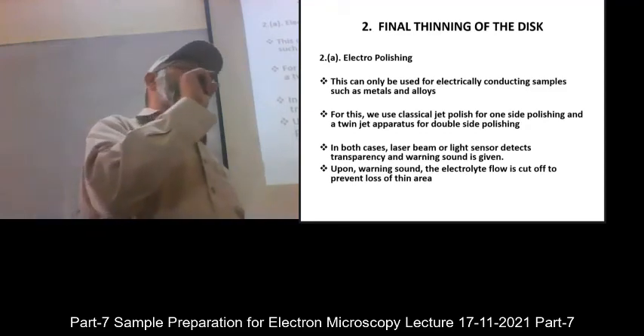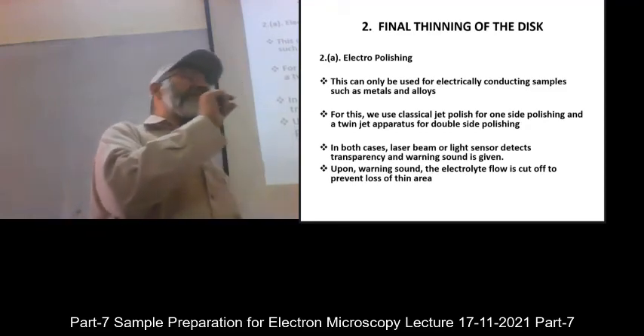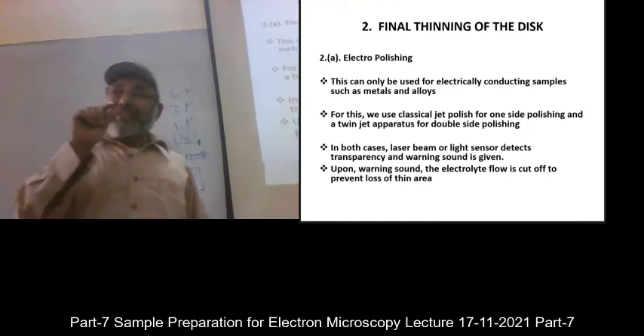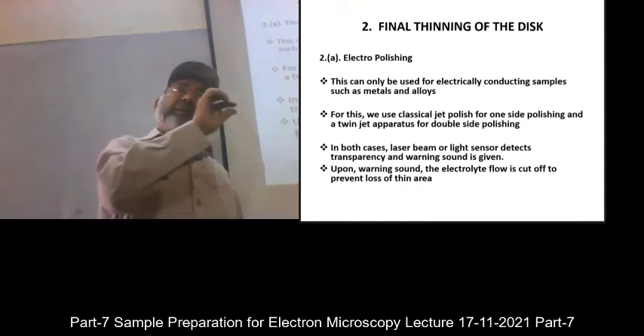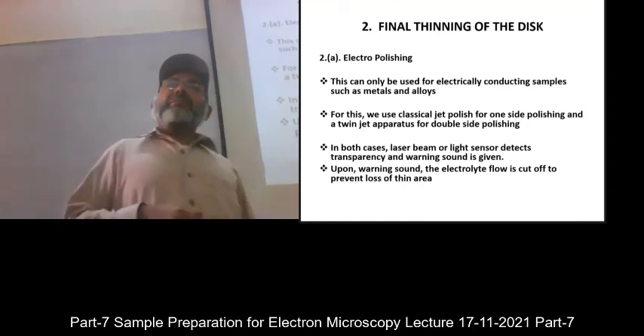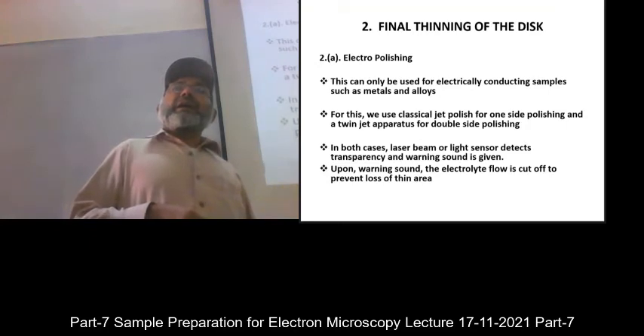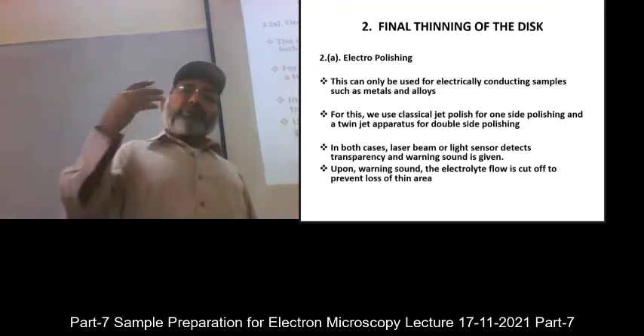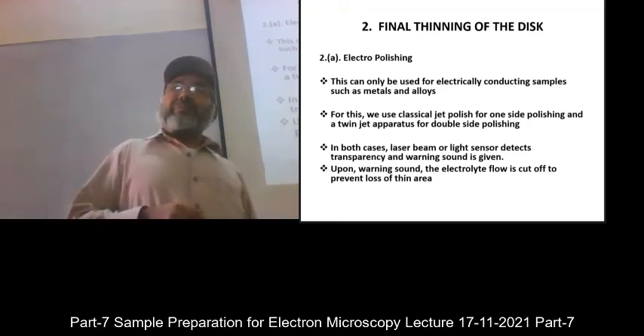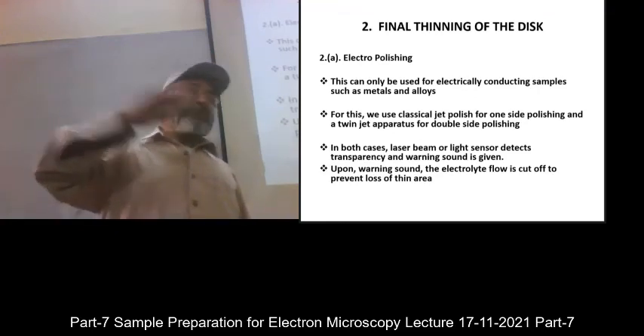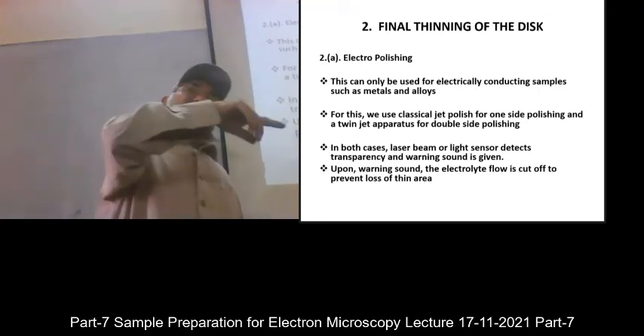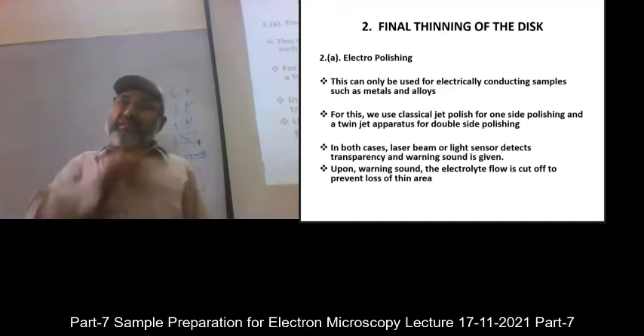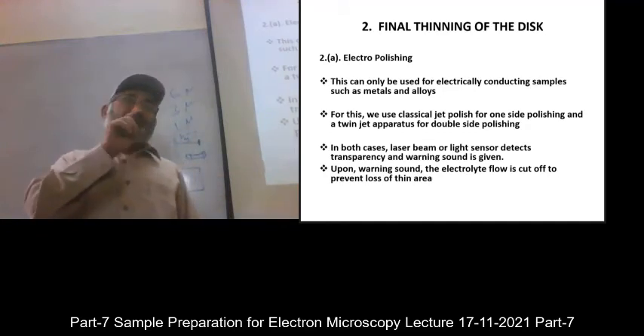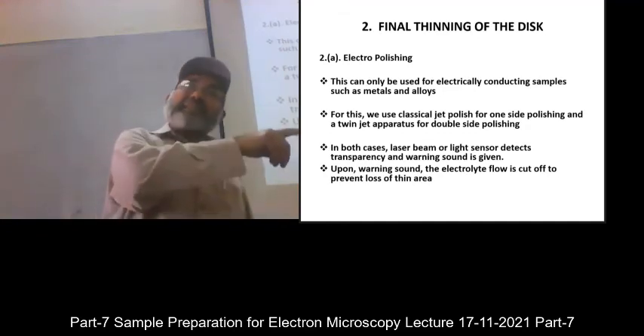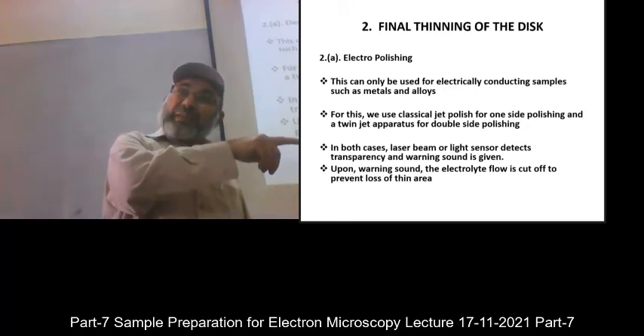Because once you get the thin area, then it is very, very risky. A little bit further thinning may get you rid of the thin area. With a thick sample, you do many things, but when it reaches there, it is a very critical stage that you recognize that this is now the best sample.